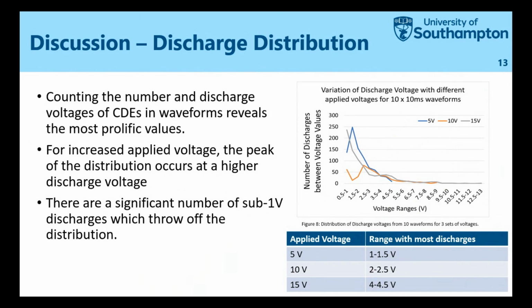But it also shows a significant amount of sub 1 volt discharges, which I think might be to do with the film thickness, or the insulation of the oil not re-establishing itself, or just vibration causing little changes in the voltage across the contact. But it does show that with increased applied voltage, the average value of discharge increases.